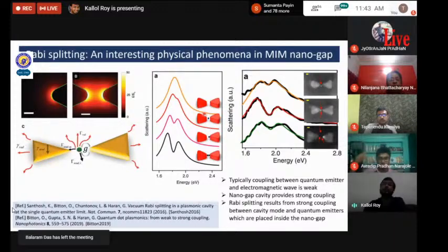So in this case, what is happening is, this metal interface is storing one form of energy, and that is interacting with nanoparticles which are placed inside these gaps. And so that changes the scattering phenomena of light, and that is observed. You can see there is a dip, scattering is less, when the interaction is strong between the cavity and these nano dots. So this splitting is called the Rabi splitting. This is one interesting physical phenomenon and very fundamental in many cases.